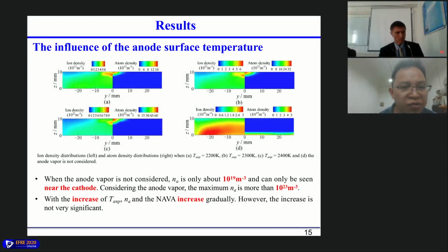We also have studied the influence of the anode surface temperature. We change the temperature from 2200 to 2400. Figure A is the anode surface temperature of 2200 Kelvin. B is 2300. C is 2400. And for figure D, we don't consider the influence of anode vapor.